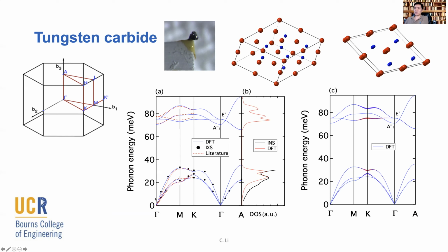It turned out nobody had actually looked at phonons in this system before, so we are the first to do the phonon measurement. Our calculation agrees reasonably well with measurement. There is better agreement along certain symmetry directions versus others, but nothing too dramatic. But what I want to point out is, at this K point, which is at the very edge of the Brillouin zone, because of broken inversion symmetry, the K and K prime points are non-equivalent.